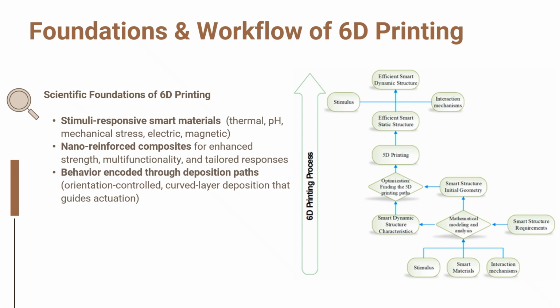Because 6D printing uses multi-axis deposition, we can orient fibers in smart domains along any direction, not just flat layers. This curved layer orientation controlled printing effectively tells the structure how to act when stimulated. The workflow on the right summarizes the full process. We start with smart structure requirements, perform mathematical and multi-scale modeling, identify an interaction mechanism, and define the initial geometry.